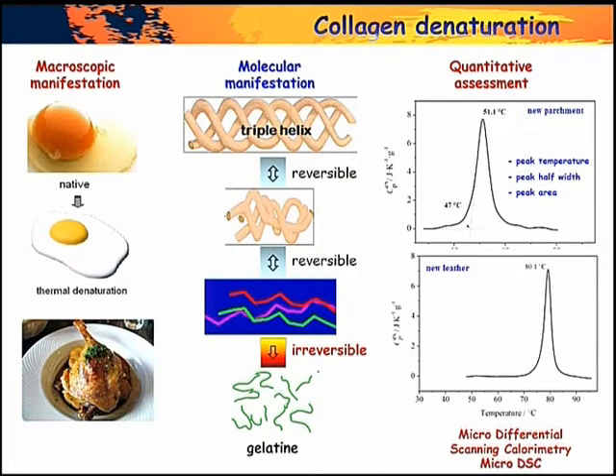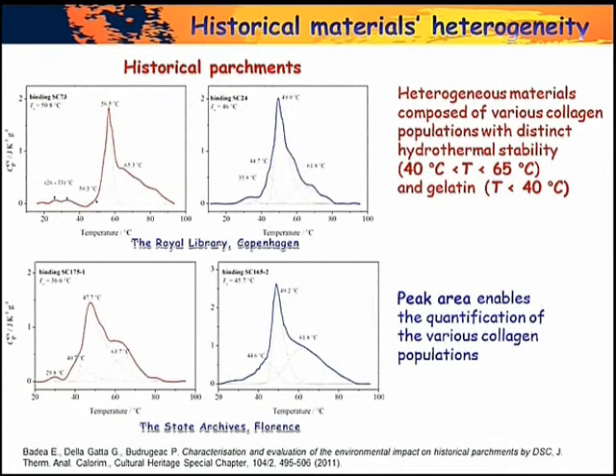Here you can see the denaturation of a new parchment compared to the denaturation of a new leather. The peak of the leather is much narrower, and the temperature of denaturation is higher, and this is obviously due to the chemical cross-linking induced by tanning. These are two very fine examples, because as I told you, both parchment and leather are heterogeneous, and also the new materials can have an intrinsic heterogeneity provoked by the fabrication technology or by the quality of the fabrication technology.